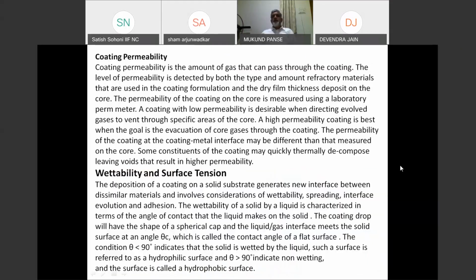The coating permeability is important for two things. When you are spraying it, some air also gets entrapped. It should be able to go out, and when the film is dried, the gases generated should be able to go out. The permeability of the coating, there is a measure, a permeameter, used for measuring the permeability of this coating.